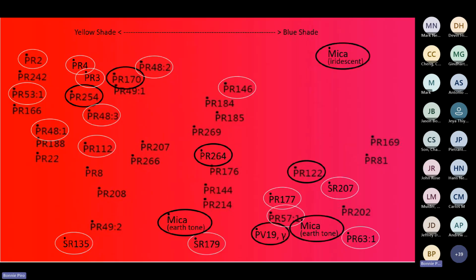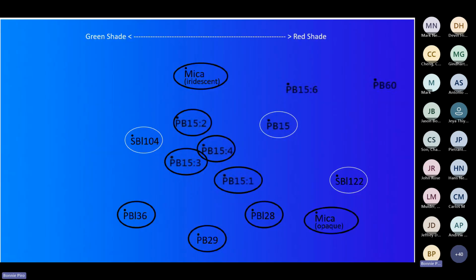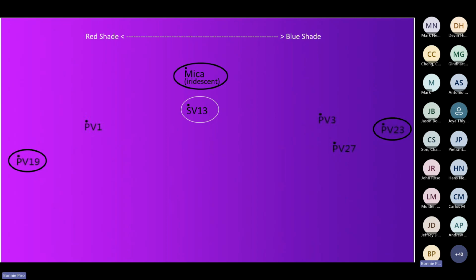And in the red space, the pigment red 254 is probably one of the more yellow ones, and then the red 122 is to the blue side. And green, a little less numbers of colorants to fill that space, but it does go from the yellow shade to the blue shade. And same for the blue space in here. So we've got options to cover the full space. And on the blue shade, the violet 19 is to the red side, while the violet 23 is to the very blue side.